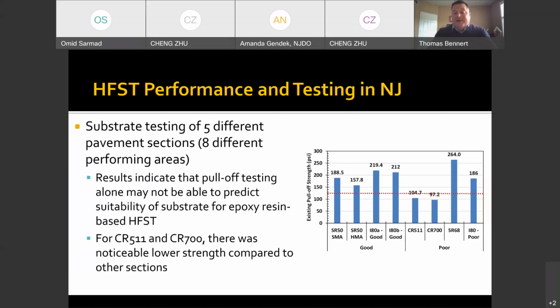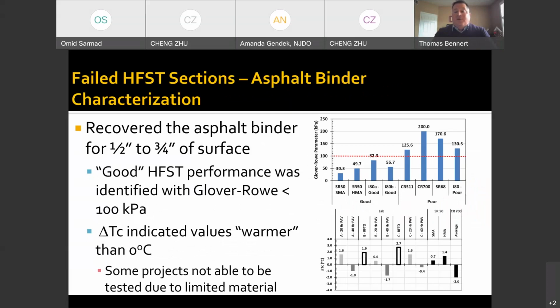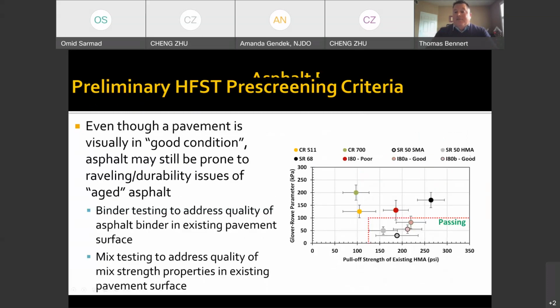So it shows that there's some level of performance there in the field that's related to the pull-off strength, but does not correlate exactly. When we also took a look at the asphalt binder properties, we saw something very similar, where again, what you have is you have in some conditions a very good performance, and in other conditions, it was higher and above. And you can see here in the 4 sections that performed very well, they were all below this threshold. In those 4 sections that performed poorly, they were above the threshold. So this parameter from the binder side gives us a relatively good handle on this general durability of that asphalt binder. When we combine the 2 together, that gives us our best level of performance.